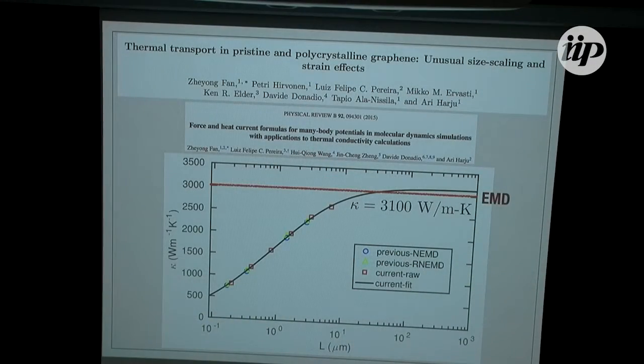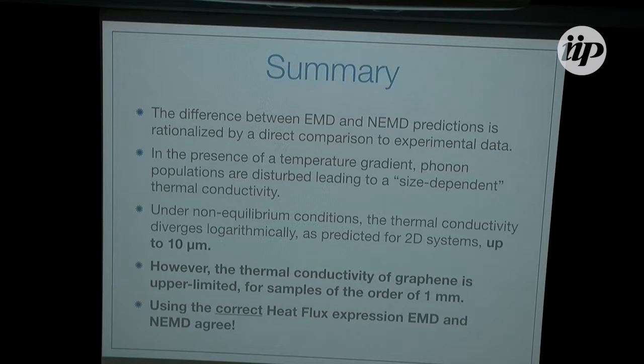When we did use the correct expression, we obtained a thermal conductivity of about 3,000 watts per meter Kelvin with equilibrium MD, which is within the error bars. It's the same as we obtained from non-equilibrium MD. So the results do agree. We are finishing up this paper, and we should send it out soon. So as long as you use the correct expression for the heat flux, equilibrium MD and non-equilibrium MD agree.